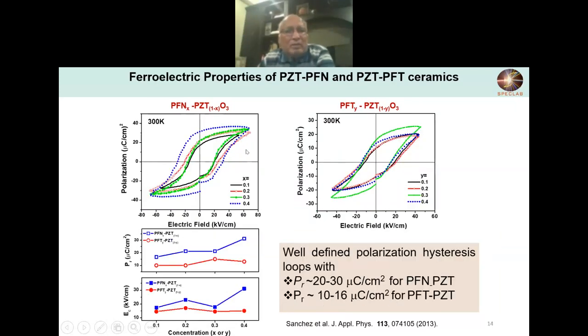Here are the ferroelectric loops of the PFN-PZT and also PFT-PZT. You can see that as you change the composition, the remnant polarization changes, it increases. At 0.4 it is maximum, and at 0.1 it is lowest. Here we have plotted how the remnant polarization changes as a function of concentration. You will see that probably the best one is around 0.2 to 0.3.